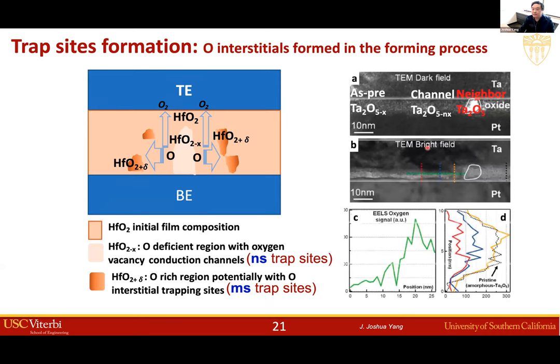In fact, this has been observed in tantalum oxide. And in this experiment, we have the as prepared film is a suboxide. And then when you electrically form it, you create even more oxygen vacancies in the conduction channel. But that process actually pushed some oxygen to its neighbor. And we find in the neighbor, actually, there is tantalum pentoxide. So basically, this oxygen got pushed away to mix the suboxide into a stoichiometric oxide. This can also be seen by other data.